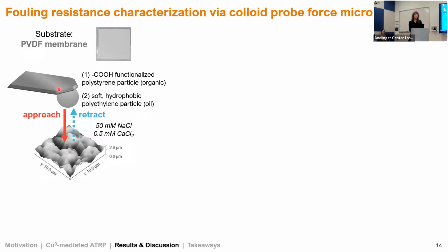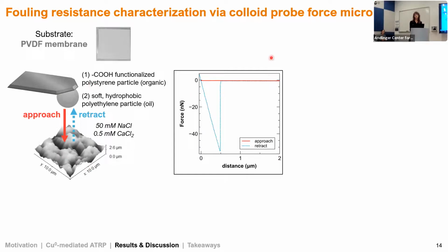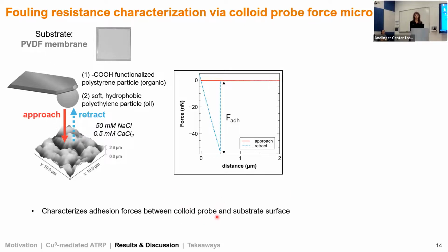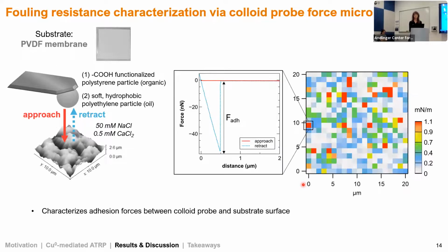So we bring our probe into contact with our substrate, and then we retract, and that results in a force distance curve, something like the example shown here. Based on the maximum depth of our retraction curve, we can determine the adhesion force between our colloid probe and the substrate surface. The higher the adhesion force is, the more likely the foulant is to attach. So that's bad. We want low adhesion. Because these are stochastic in nature, we perform this many times for each substrate, and that gives us an adhesion force map like the one shown here. Each of these figures represents 400 force curves.